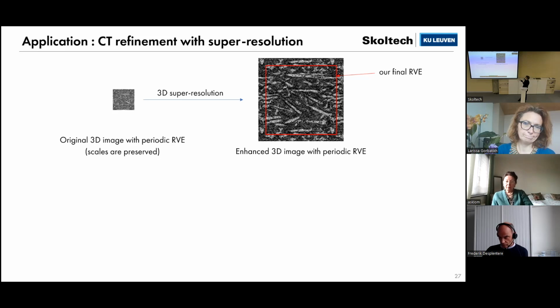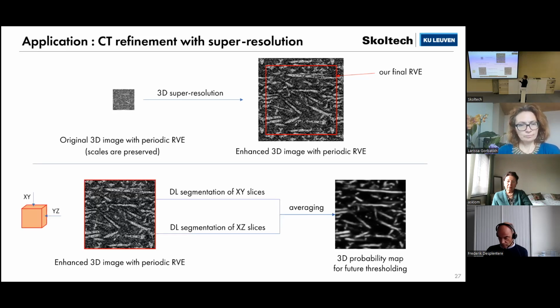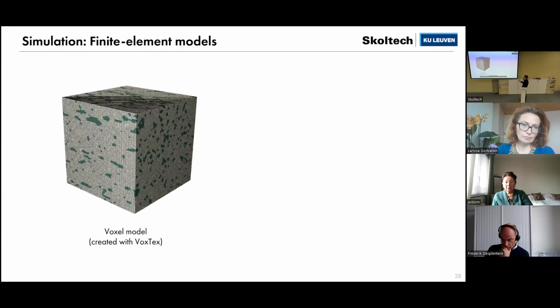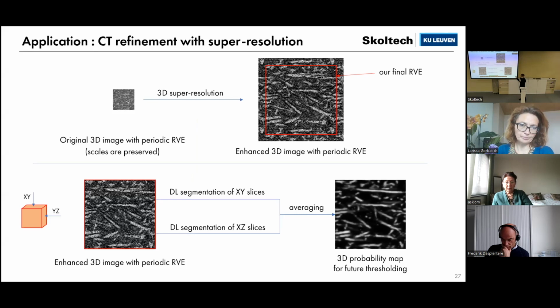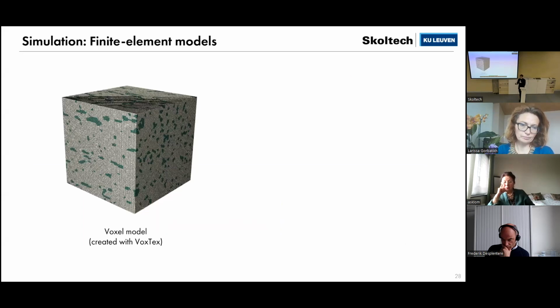Of course, it has some artifacts due to the fact that it was generated. But using deep learning segmentation again, we were able to identify where our fibers and matrix were. Here you can see the probability map. White is fiber and black is matrix, and the segmentation was done in two directions to have averaging of the results. Using these probability maps, we can already treat it as a classical CT image, and we can input it into any other modeling software.